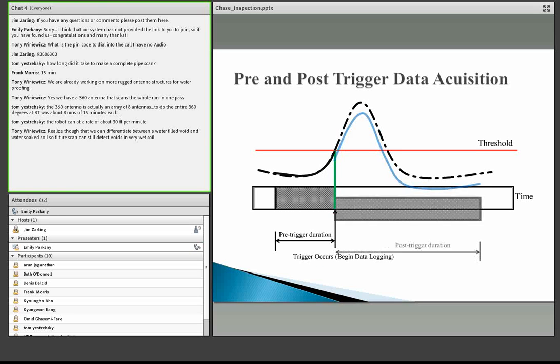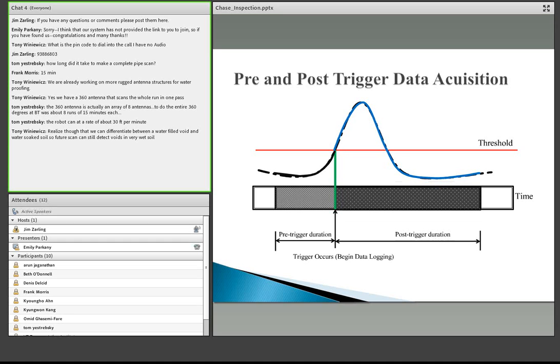Significant effort went into developing the ability to detect a loading event, but also collect data that was happening before the loading event was detected. So we have to be continuously collecting data from the bridge, detect when a load event occurs, go back and retrieve some of the data that occurred before the loading event, store some of the data after the loading event, and all of that information is needed in order to extract the thermoelastic signal from the data that's acquired.